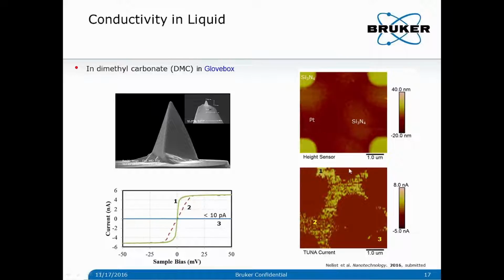And so here is an example of a conductivity measurement based on PeakForce tapping mode using this nanoelectrode probe in a glovebox, of course, in liquid. And the liquid is DMC. So this sample is a platinum electrode partially covered by silicon nitride. And the conductivity map clearly differentiates the exposed platinum region here.